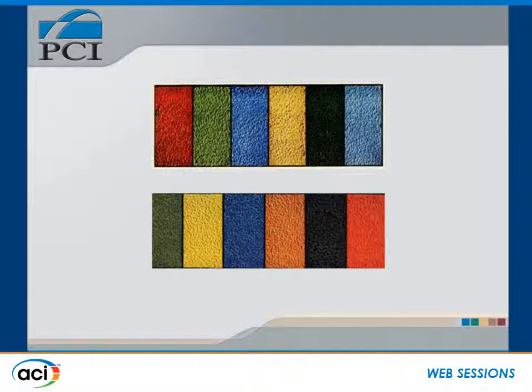The strength of the color of the concrete made with colored aggregates depends largely upon the extent to which the exposed surface is composed of aggregate particles. A coverage of 80% is about the minimum which produces satisfactory results. Most mixes obtained a maximum of 85%.